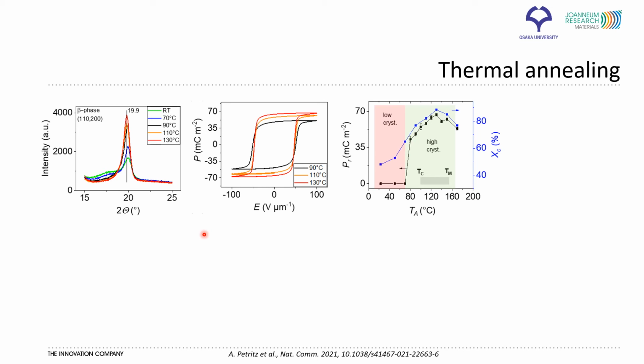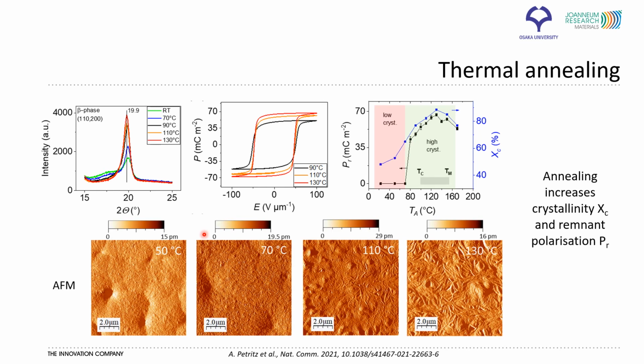The change in crystallinity is also illustrated in these AFM images. With higher annealing temperatures, the lamina-like crystallites increase in size and density.